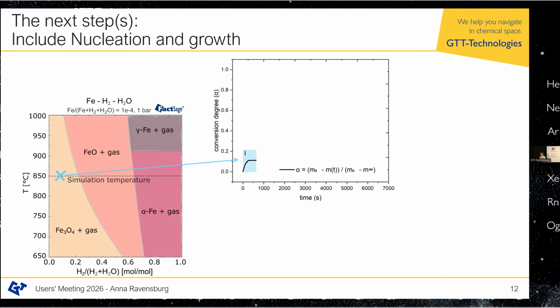And how they look is like this, of course. We're GTT, so we start with a phase diagram. This phase diagram plots the temperature over the H2 to H2 plus H2O ratio. And we are trying to look at how the phases nucleate, but for that we have to have them nucleate one after the other. And that's why we select conditions for our pellet reduction experiments, where we select these H2 to H2O ratios so that we are in a thermodynamic region where it's only possible, for example, to first form Fe3O4. And what you see is this corresponds to this blue conversion curve.